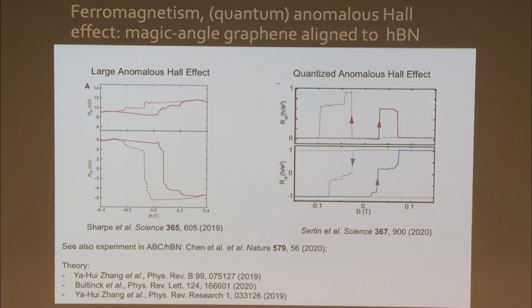And in fact, magic angle graphene, in this case, it was aligned to hexagonal boron nitride. You have to do a trick to break the symmetry of those A and B atoms. But this system holds now the world record for the quantum anomalous Hall temperature for any system, okay? Any semiconductor, etc.